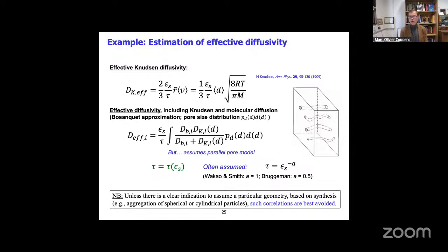So you could use a model if you know through synthesis that it's just an aggregation of platelets, an aggregation of pseudospherical particles, then you can use models based on, say, stacks of spheres, overlapping or not. And indeed, you have relations then in this case between the tortuosity and the porosity. This goes back even all the way to Maxwell in the end of the 19th century, who studied these types of relationships and finds a relation between tortuosity and porosity. However, if you don't know that, such correlations are really best to be avoided.